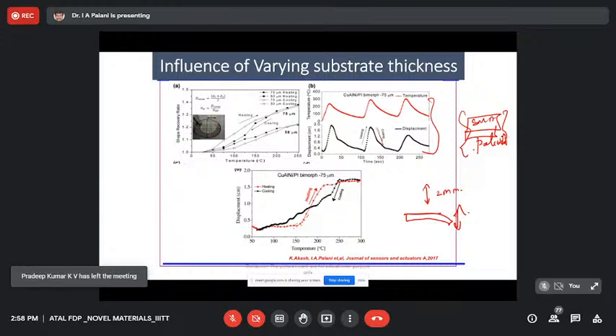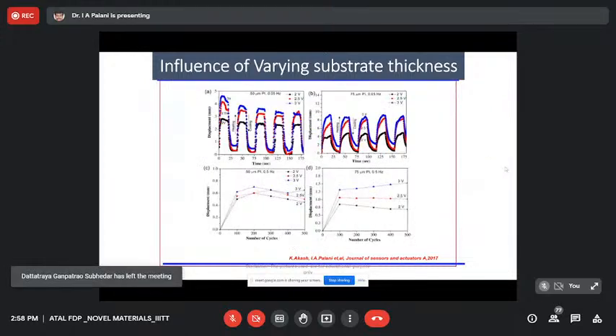For that, we chose two different types of polyimide: one is a 75 micrometer polyimide and another one is a 50 micrometer polyimide. We could see how the response behaves with respect to the 75 micrometer polyimide as well as the 50 micrometer polyimide. Basically, at 50 micrometer polyimide, we could get a proper narrowed down system. With respect to a variation in voltage, we could see an increase in the displacement. At 50 micrometer polyimide, if my applied voltage is 3 volt, we could get a displacement of around 4.5 mm.